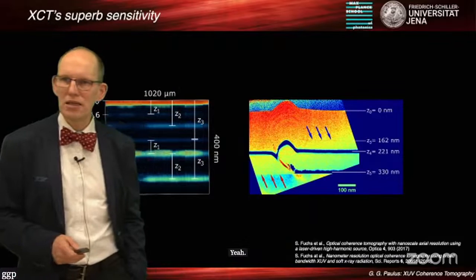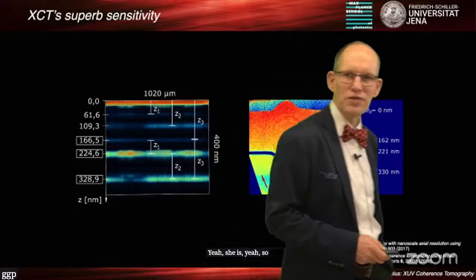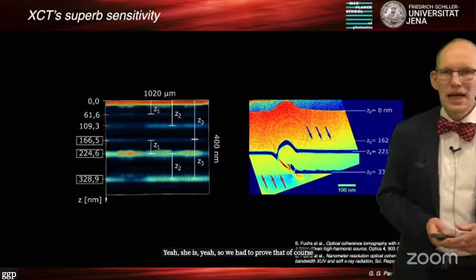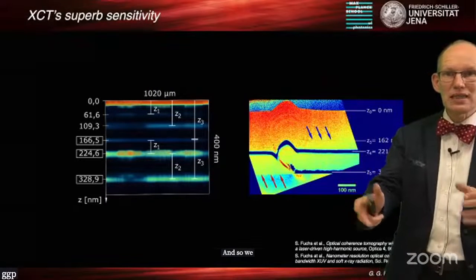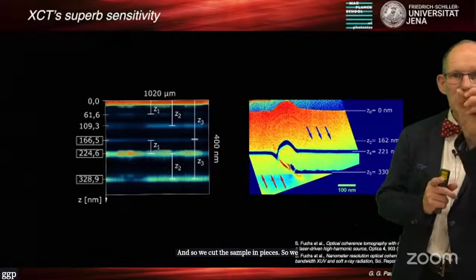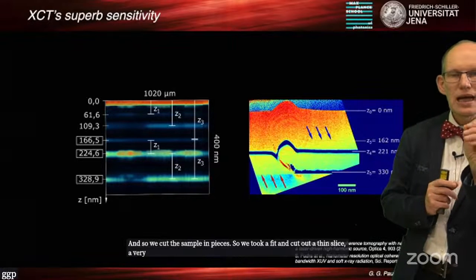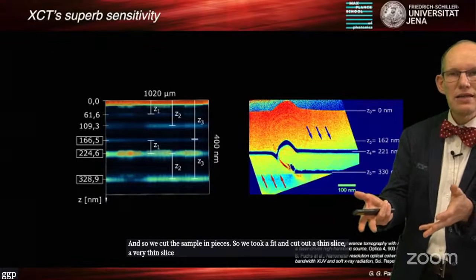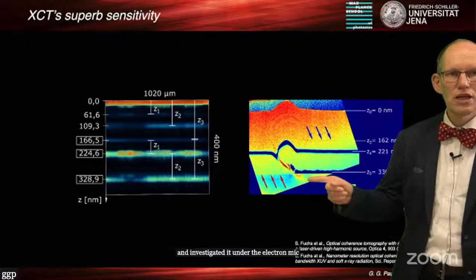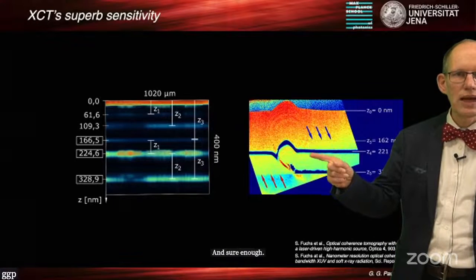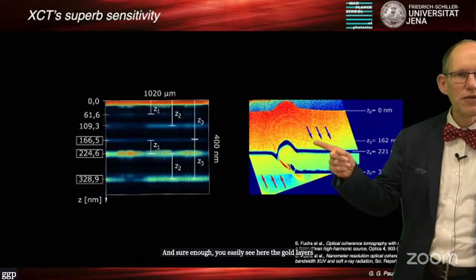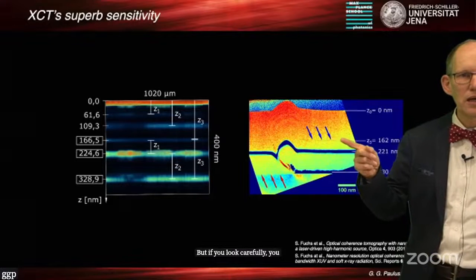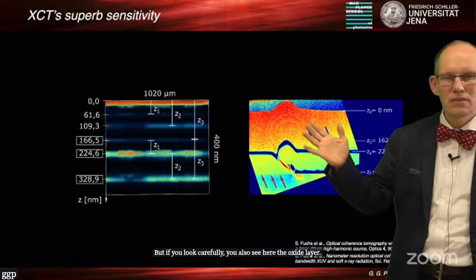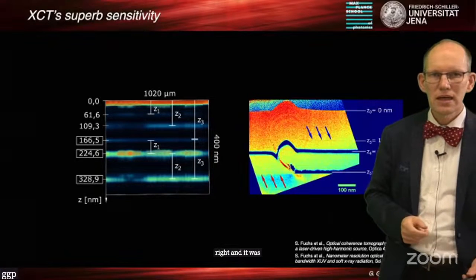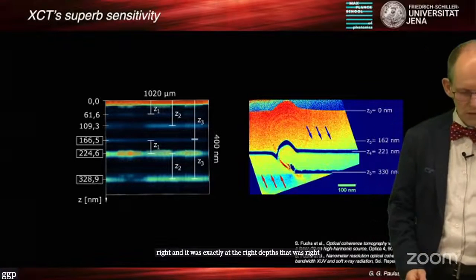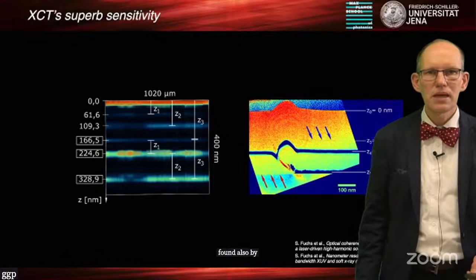So we had to prove that, of course. We cut the sample in pieces. We took a FIB and cut out a very thin slice, and investigated it under the electron microscope. And sure enough, you easily see here the gold layers. But if you look carefully, you also see here the oxide layer, and it was exactly at the right depth that was also found by XCT.